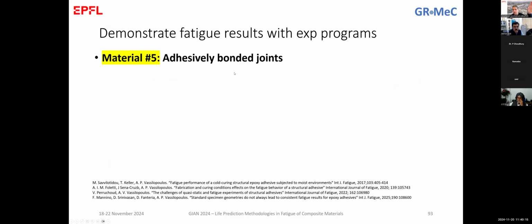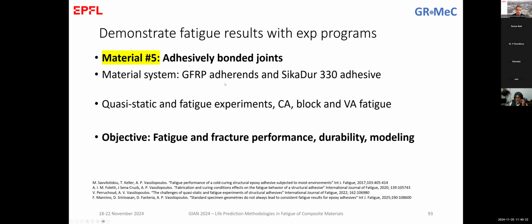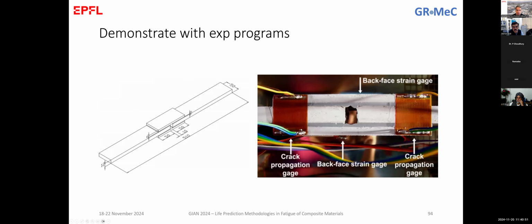So here we talked about adhesives, we talked about composites, and now is when we mix these two and we make adhesively bonded joints. And there we did again a lot of investigations in the past. And of course, the set objectives there were again the fatigue and fracture performance. Now we are also introducing the fracture behavior of the materials, in terms of long-term performance, which means durability, and of course all these investigations are for achieving finally a modeling of the material. In this case, here is a testing program with double lap joints. This is the geometry, and this is the focus on the area of the joint, where the objective is, of course, to investigate the fatigue performance.